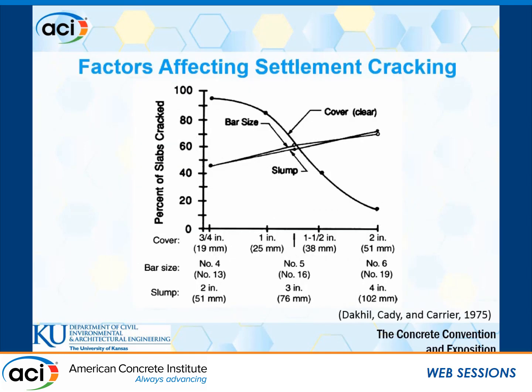The factors affecting settlement cracking are: the shallower the cover you have, the more likelihood you will have settlement cracking. Likewise, when your bar size increases and when you use high slump concrete, you're more likely to have settlement cracking.